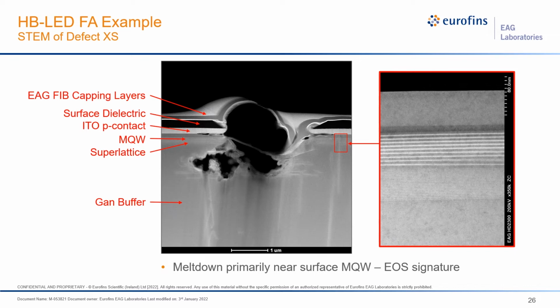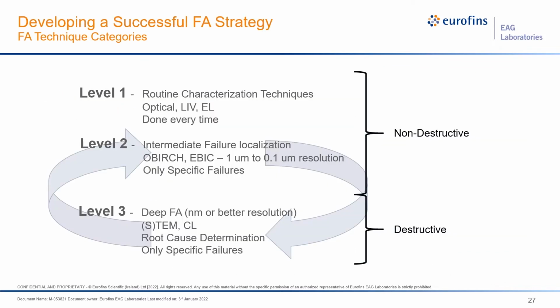So ultimately, in this case, the biggest problem we're having is that the actual destruction of the sample, or creating this failure, we didn't catch it early enough. So it was allowed to go on long enough to where the sample really consumed the defect that caused the issue to begin with. So we kind of have to circle back a little bit here to try to understand this a little bit better.